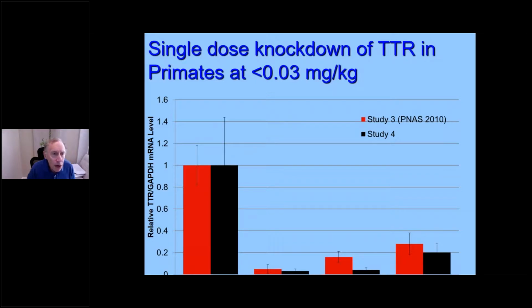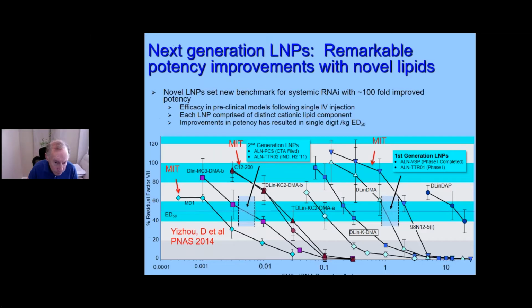And I probably put 2 areas that would end up being important that we really looked at. One was, could we use less and less siRNA? And by the way, multiple companies now sell these reagents based on what we did. There's at least 4 different companies like Sigma Aldrich, Clone Tech, StemGen, and others that sell these reagents. But what we would do over time, again working with Alnylam, is keep on improving and improving the knockdown, so you need less and less material. And the next slide just shows what we did.